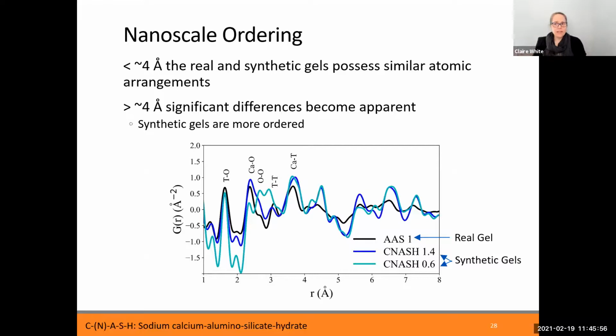If we look at the alkali-activated slag system, we are lucky that we only have reacting glassy slag, which is a calcium, magnesium, aluminosilicate type glass. We have the CNASH gel that precipitates, and occasionally you get a very small amount of a secondary phase like a hydrotalcite-like layered double hydroxide, but it tends to be in very small quantities. So what we've done here is actually compared the synthetic CNASH gels to the CNASH gel in an alkali-activated slag after we've subtracted the unreacted slag from the data. So what's shown here on the screen in the black, that's actually the real CNASH gel after we've subtracted out the contributions from unreacted slag.